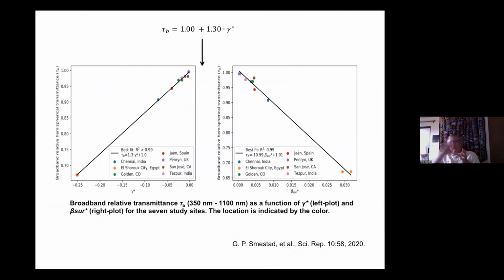We took the transmission over all the wavelengths, 350 to 1100 nanometers, and took an average value of the transmission in that band. And you see it gives a linear relationship. We did the same thing with beta subsurface versus the hemispherical transmission. And this tells you that there could be some relationships which stretch across different sites, that this modified Angstrom equation has somewhat of a universal appeal and utility. And so we've explored it for its utility as an empirical approach to modeling the transmission of glass that could then be put into models for CSP and PV.